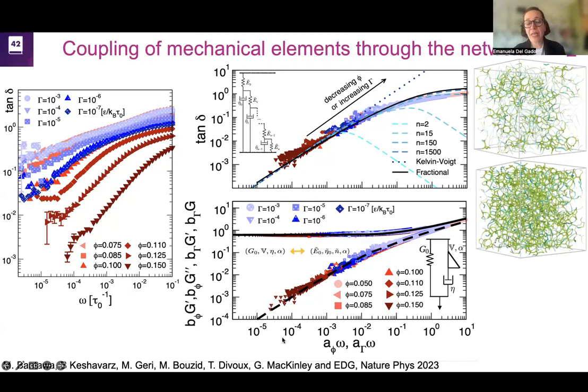And then once you have this horizontal shift of the frequency, you can keep that shift and shift only the y-axis to obtain a unique master curve of the whole rheological spectra. And what is interesting in doing that is that, in fact, we understand